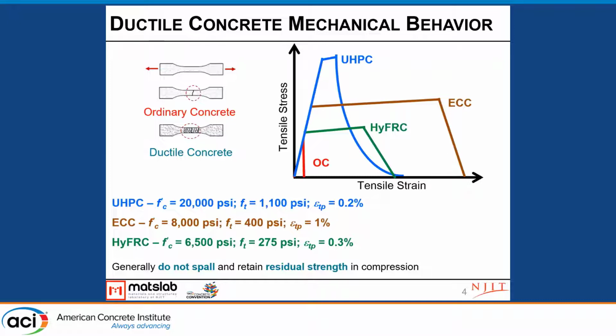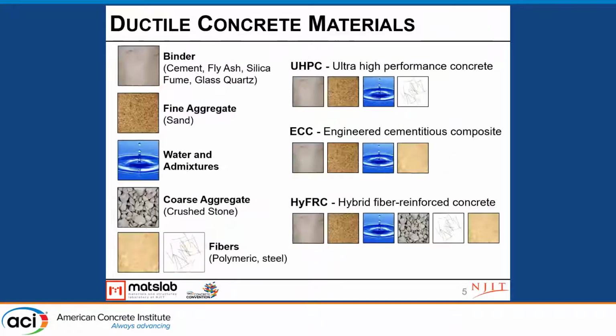Also, I have provided a summary of the mechanical properties of these materials, and these materials generally do not spall and retain residual strengths in compression. On this slide, you can see an overview of the mixture designs and constituents of these three different ductile concrete systems. In UHPC, we have binders, including cement and SCMs like silica fume, ground silica, and so on, depending on the mixture design you're using.